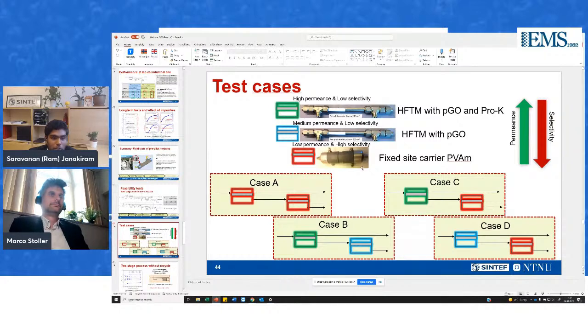So one way is to look at both of them, but the other way is that we were only able to scale up only a couple of membranes. But when you look at the actual performance of different membranes with this recipe, we can actually tune the selectivity and permeance to whatever extent we like based on the component compositions. So in that case, we have a possibility that we can also make a membrane which is highly selective from the system. Thank you.